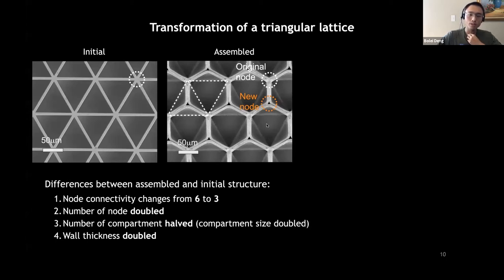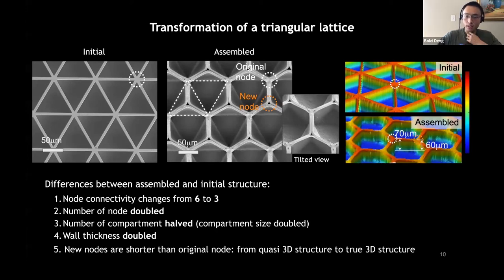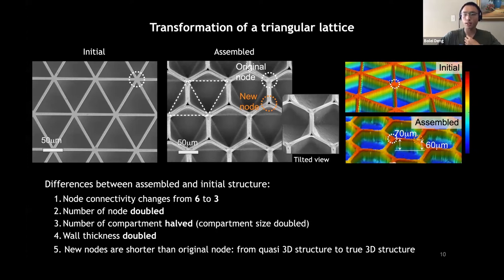Because the structure is still attached to a substrate, the bottom remains triangular while the top is hexagonal. From the tilted view and profilometer 3D scanning image, the newly formed node is slightly shorter than the original node, meaning the transformed structure becomes a true 3D structure compared to the quasi-3D initial triangular lattice. As we will show, all these changes — topological changes and height profile changes — contribute to the property changes of the cellular structure.